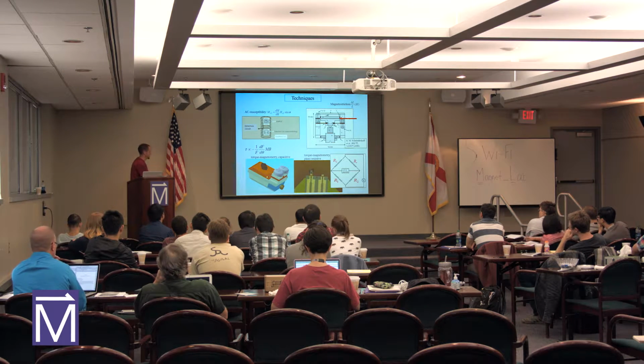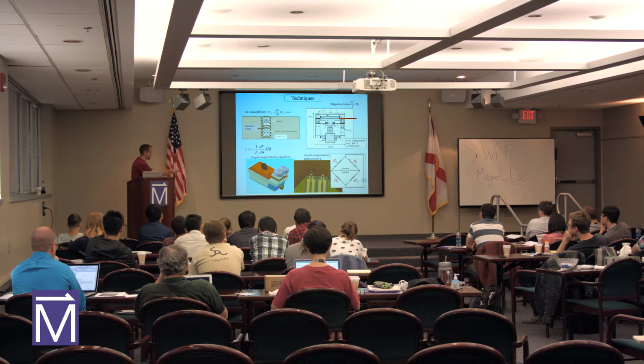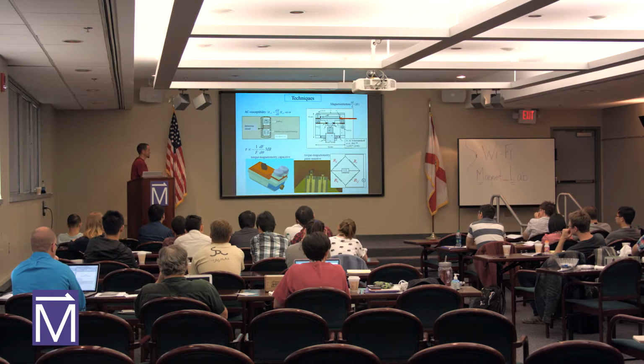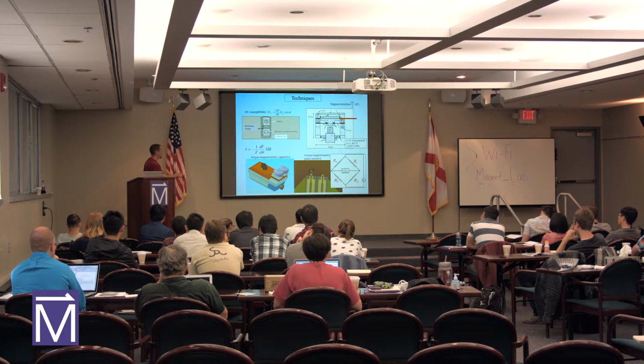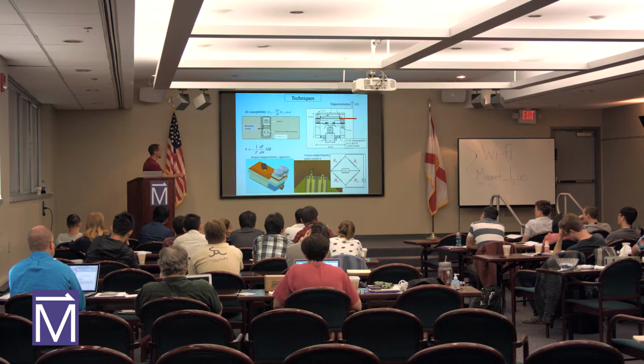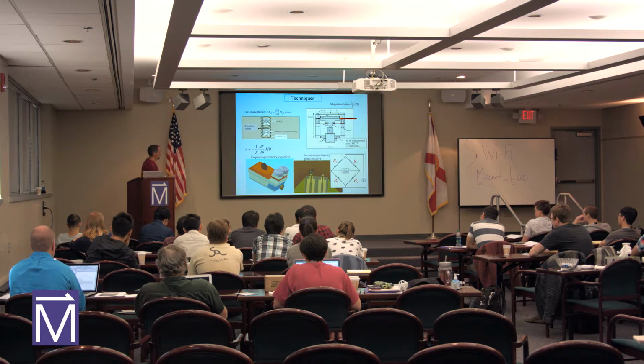Another way to measure Fermi surfaces is again through torque magnetometry. I saw Eric discussing this a little bit as well. Here's a block of a sample on this foil cantilever, usually made out of beryllium copper. And there's also a bit of copper foil beneath this bit of foil, and they're separated by some insulator, a little bit of G10, something like that. And we measure, again, as a parallel plate capacitor, the capacitance between these two pieces of metal. When we sweep the magnetic field and the magnetization of the sample changes because of quantum oscillations, this foil wants to move up and down, and we just measure the capacitance of it. This works in a lot of cases and for larger samples, and we can use different thicknesses of foils. That lets us be very versatile, but it's not the most sensitive option.